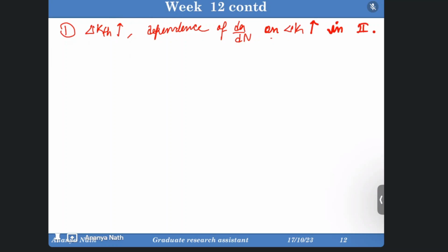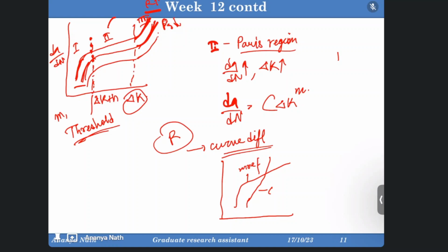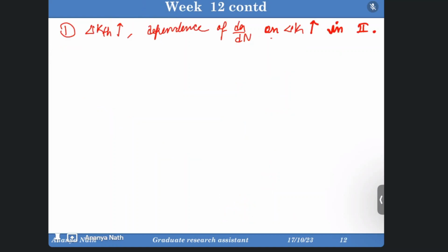So mid-range is the most crucial zone, because you see this threshold value will be dependent upon the exponent n and the stress ratio and the reinforcement. Most importantly, whatever particle you are adding and whatever size distribution you are adding, depending upon that, the threshold value will be decided. So we are not considering this 1 and 2 portion here. We are only concerned about the Paris region, which is the second stage. So if the del Kth is more and if the dependence on the Kth is more in Paris region, this can occur.